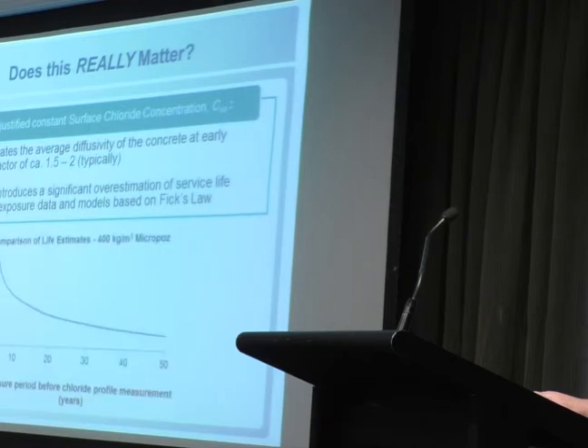And that just shows an example of what exaggeration there is for one of the concretes on the exposure site block, depending on when you measure the profile. So it can be significant, and that's a problem, because a lot of the empirical Fick's law models are based on that assumption that the chloride profile, the chloride concentration is constant and doesn't change.